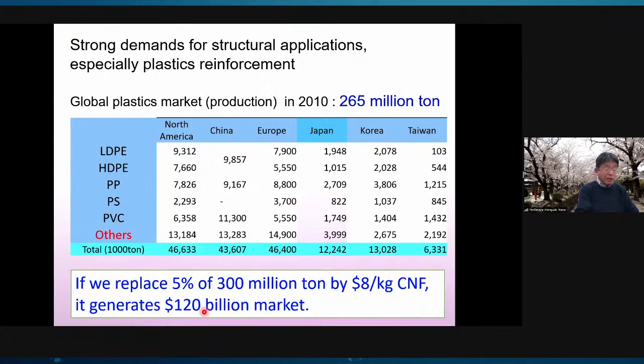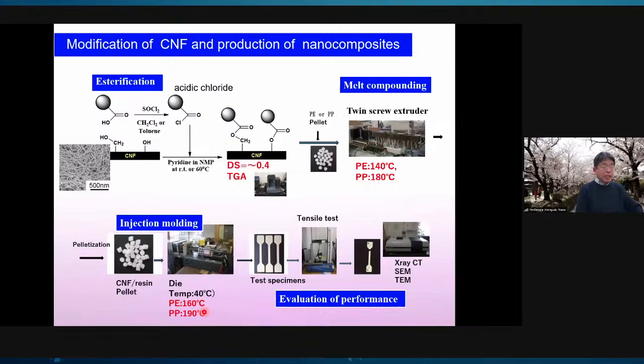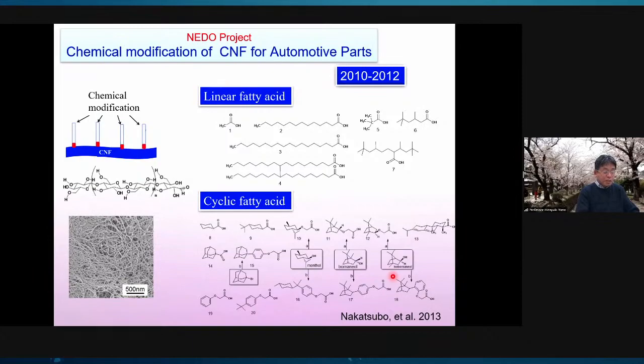Then we studied the reinforcement of thermoplastic by CNF using melt compounding. This is a production system which consists of esterification of CNF, melt compounding of chemically modified CNF with PP and PE, and injection molding of the compound to make nanocomposite samples for the test. We studied the effect of the functional group incorporated on the surface of CNF for the reinforcement of PP and PE, polyethylene, using linear fatty acid and cyclic fatty acid.